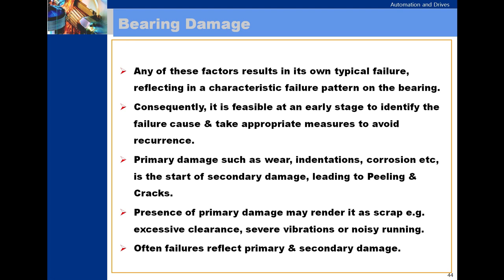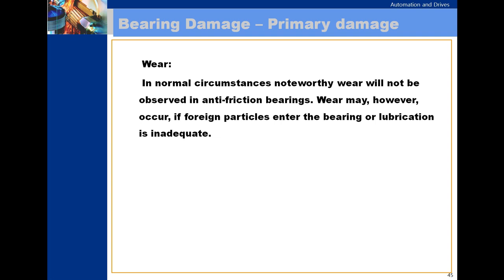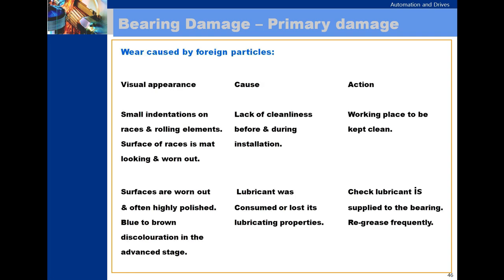Presence of primary damage may render the bearing scrap, for example through excessive clearance, severe vibrations, or noisy running. Often failures reflect primary and secondary damage. In normal circumstances, wear will not be observed in anti-friction bearings. Wear may, however, occur if foreign particles enter the bearing or lubrication is inadequate. Wear caused by a foreign particle.